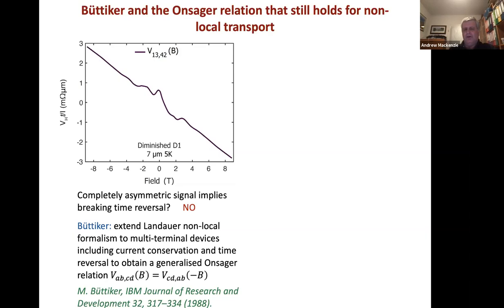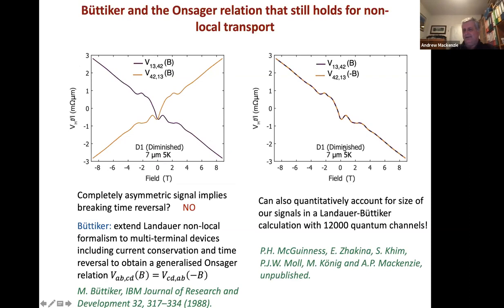So there's a very famous paper by Büttiker from 1988, where he pointed out that whatever is going on, whatever regime of transport you're in, there is one generalization which has to hold. And that says that if you reverse the current and voltage contact pairs and reverse the field, you have to see the same thing again. So that's what you get from this crazy looking Hall effect when you reverse the pair configuration. Then you plot as the negative of the field to try and do the entire Büttiker-Onsager operation. And you see that absolutely perfectly the data lie on top of each other when you do that.